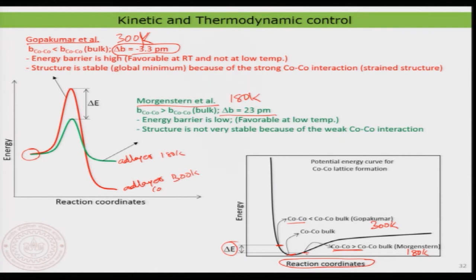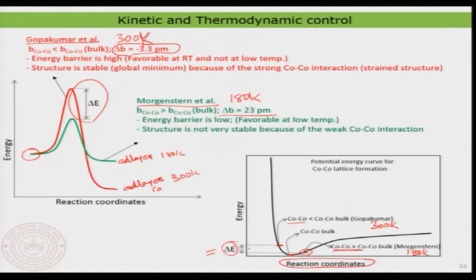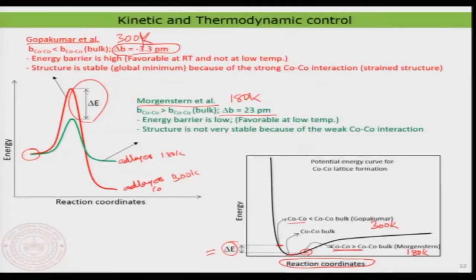The reason is very simple. You can see here that the cobalt-cobalt distance is much more relaxed in the 180 Kelvin case compared to that in the 300 case. So that means in order to pack the atoms in a compressed way, you need to cross a much larger barrier than the other case. So that is this delta E, and the delta E in this diagram somewhat corresponds to the delta E in this diagram. So that means in order to pack the atoms compressed on the surface, you need to cross a large barrier. But if you want to have an atom relaxed at the interface, you need to cross a lower barrier. So that means at 180 Kelvin, you cannot form the structure as shown in the red curve, because the barrier to cross is very, very high.